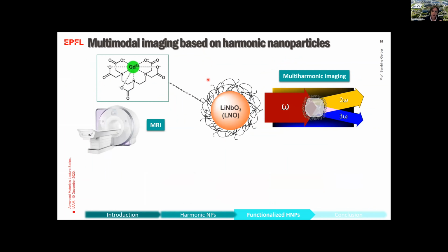Then another important aspect that we investigated with these nanoparticles was the possibility to combine the multi-harmonic imaging capabilities, using both the second and third harmonic generation, with magnetic resonance imaging, thanks to the conjugation at the surface of the nanoparticle of gadolinium-based chelates.